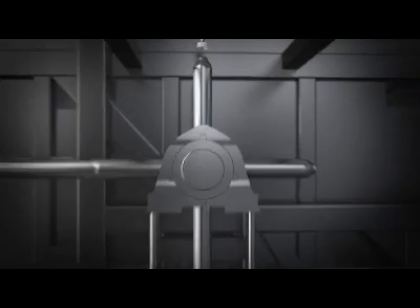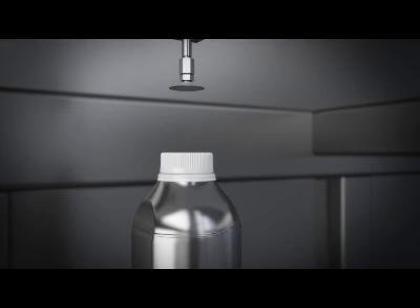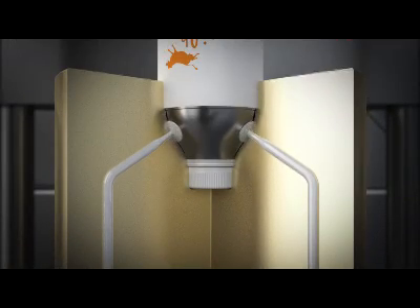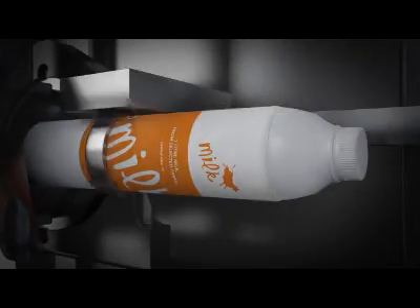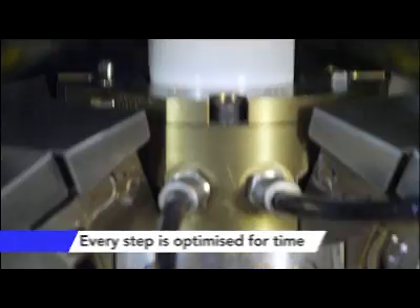This is actually the fastest injection molding in the world. The way it works is that we apply the closure on the mandrel, then we put the paperboard sleeve on the mandrel, and then we make the injection in just 40 milliseconds. We open the mold just before the plastic is frozen, meaning the plastic is semi-liquid when we open the mold.